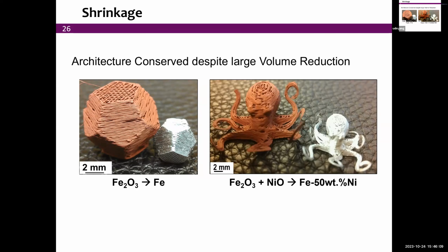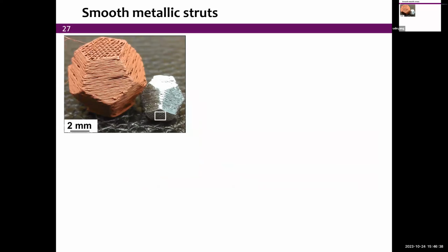But you say, well, that's not very useful because your dimensions are changing. Yes, but it's reproducible. And that's something that happens routinely in the powder metallurgy industry, where the shrinkage may not be only 10 or 15%, but as long as you're reproducible, you can oversize and then end up with objects that are close to net shape. And you may need a bit of modeling, a bit of machining to achieve your final shape. Maybe not on a complex shape like this, but maybe on structures like this.